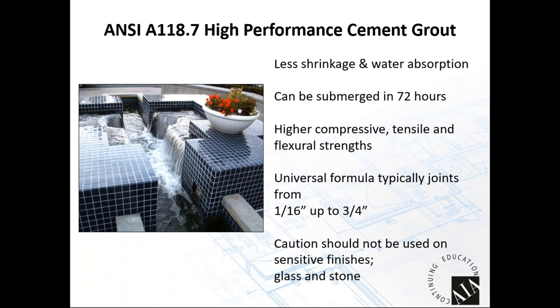Some of the other advantages of these high performance cement grouts is that there's less shrinkage and water absorption. They can be submerged in water in 72 hours, so a lot faster curing time on them, higher compressive, tensile strength and flexural strength. A universal formula typically joints from 1/16 of an inch to 3/4 of an inch.